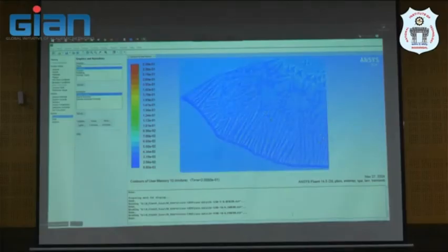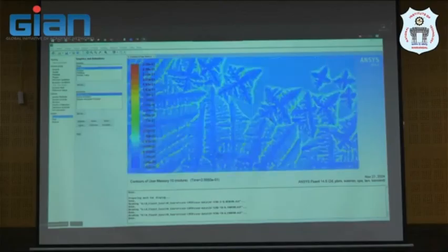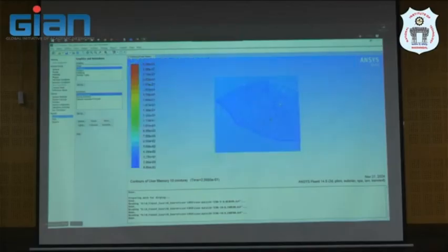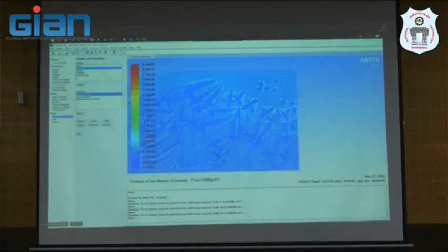Yes. Here is the microsegregation during the multiple solidification. We can see the species, the elements, are enriched in the liquid area during the solidification, like here.